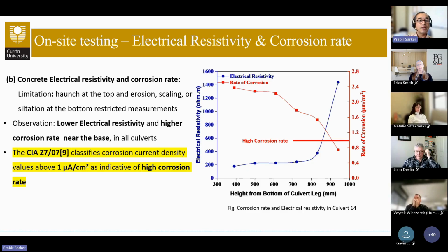So basically the electrical resistivity and corrosion rate were measured in the middle part of the culvert legs, where there was no obvious deterioration, since we needed a good surface for fitting of the instrument.